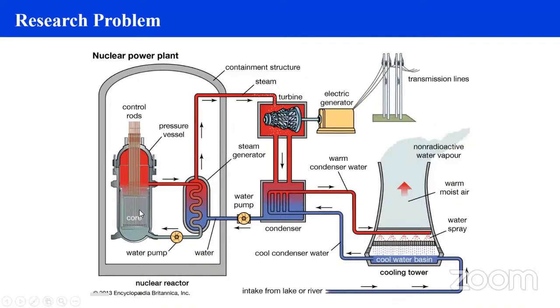So many other techniques are used, like here is a pipe where water flows inside this pipe and reduces the temperature inside the nuclear reactor. So we use supercritical water to reduce the temperature inside the nuclear reactor. And we also use nanoparticles to improve the thermal conductivity of supercritical fluids. If nanoparticles are helpful to increase the thermal conductivity of supercritical water, then the temperature inside the nuclear reactor will be reduced. And if the temperature inside the nuclear reactor is reduced, then the supercritical nanofluid is very useful to overcome this challenge, to save the nuclear reactor from blast or leakage.